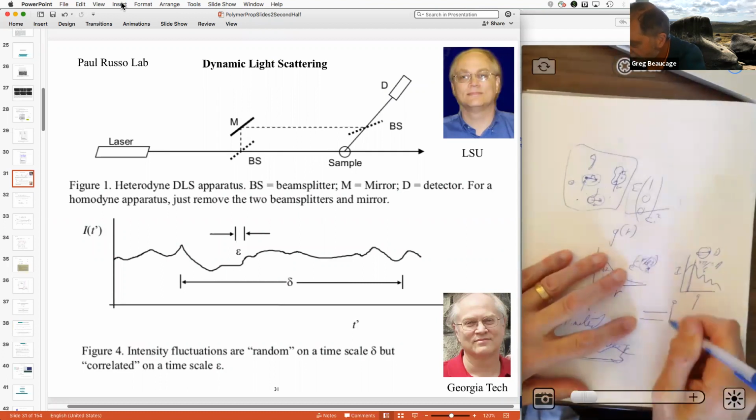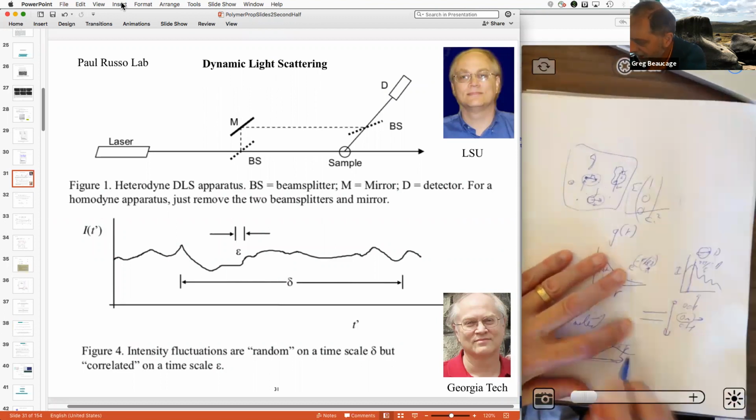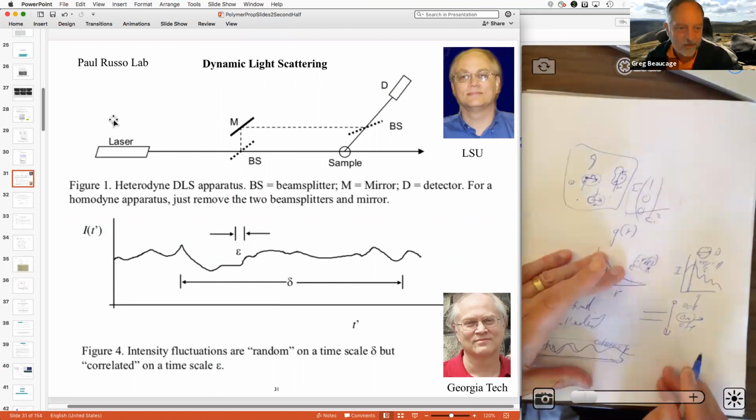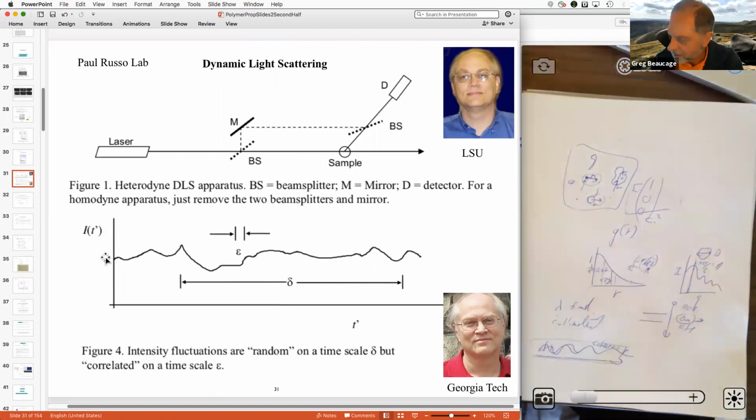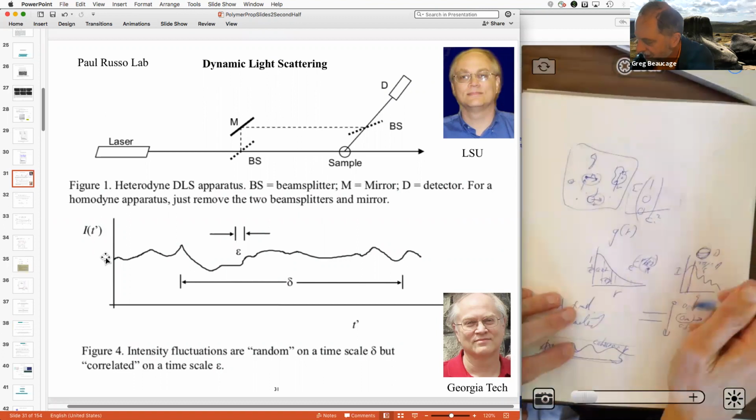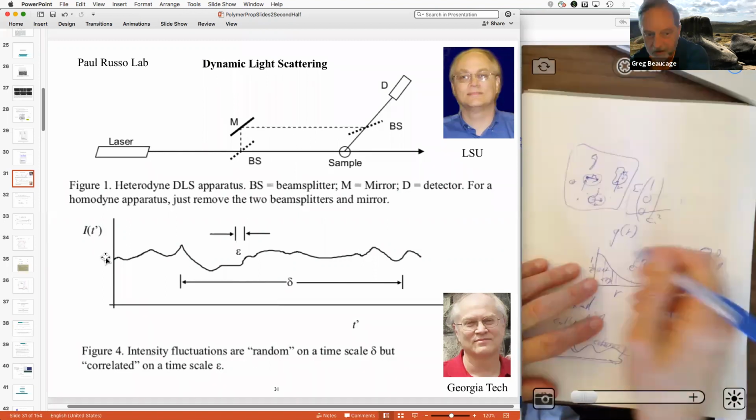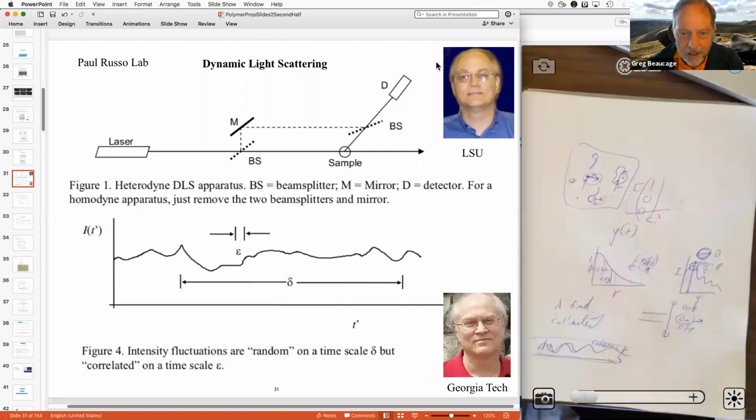So it's on and then it's off. It's off, on, off. So it blinks. Get this blinking, right? So the intensity at a given Q, maybe you'd take the Q for that peak because that has to do with the sphere diameter. So you take the Q here. So you'd set up your detector at a fixed angle, maybe at that peak. Then you just watch how it flickers.